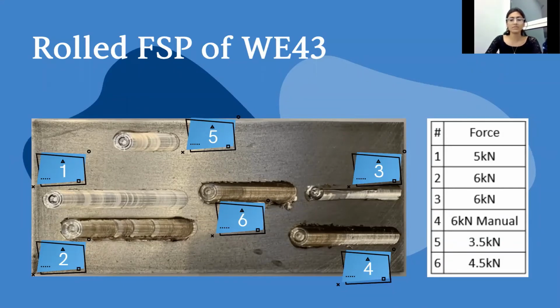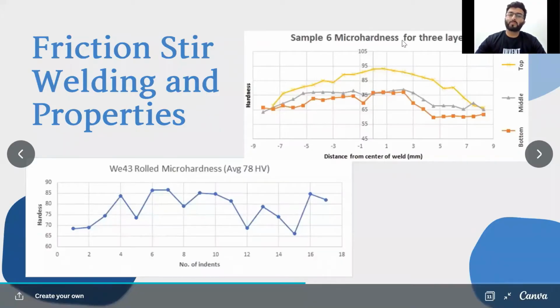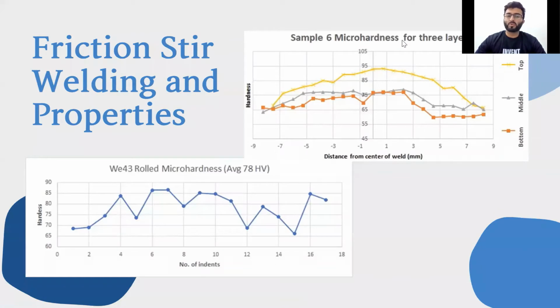However, we still experimented further by varying the loads. The figure shows the welds for the stated weld. As I have mentioned, we performed various test runs while changing the load to achieve a sound weld. The defect-free weld was analyzed and the improvement of the surface hardness was reported when compared to the base metal, as shown in the slide.